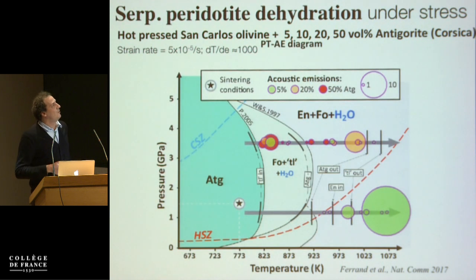So if you put that back on the PT diagram, this is the stability diagram of antigorite, ATG, as a function of pressure and temperature. You see this green space is where serpentine is stable. This is the path you would follow on the hot subduction zone. This is the path you would follow on the cold subduction zone. And this is the limit of the stability field. The dehydration happens in two steps. You have antigorite giving forsterite plus talc, and then forsterite plus enstatite plus water.